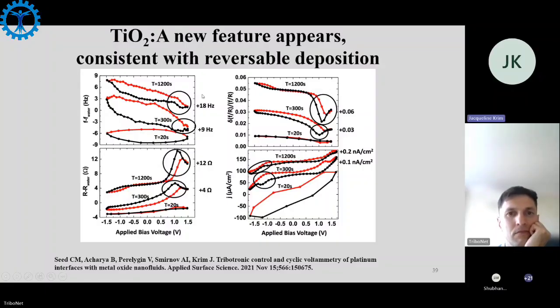Again, there's a feature showing up at slow scans in the titanium oxide that's not there with alumina. Based on all our measurements, combined with electrochemical and all kinds of things, let's just leave it at that. Getting electrodeposition at slow speed and certain voltages. And imagine what that does to friction when your system goes from a repellent nanoparticle system that's slippery to all of a sudden it collapses and penetrates the water layer on the surface and forms a film that locks in.